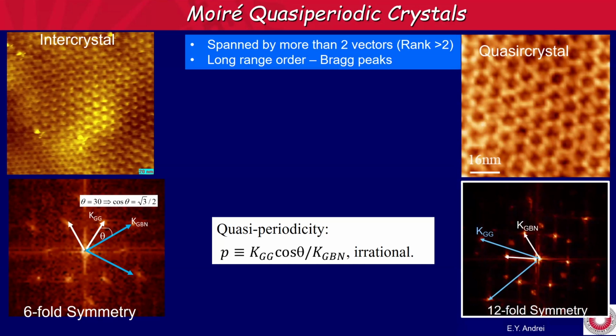And here is our quasi-crystal. Now, why is this a quasi-crystal? Here is the KGG and KGBN, blue and white. Now you take a linear combination of KGG and KGBN, and I'm getting this yellow one. There's a very special case here: they're exactly the same length as the GBN one, but they're 30 degrees to it. So now I have a dodecagon, 12-fold symmetry, a Bravais-forbidden symmetry. So Paul Steinhardt is happy.